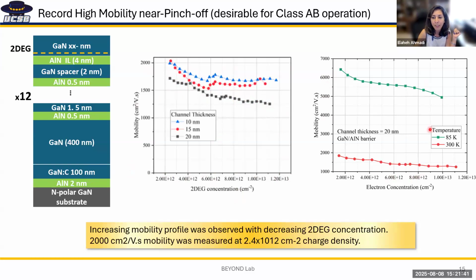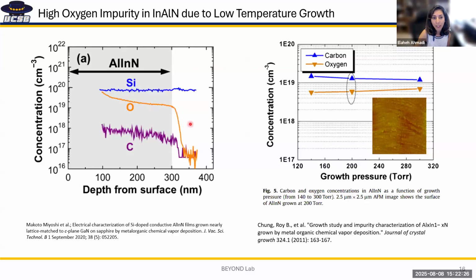And when we perform these measurements at low temperature, because then we are eliminating optical phonon scattering and all that, it's easier to see if things like ionized impurity scattering or interface roughness affect the mobility. And we saw even at low temperature, as we go to lower charge densities, the mobility increased. So we were quite excited about this, and we showed a record mobility of around 2000 near pinch off. But then the question was whether this is due to the barrier, that we have a digital barrier. So we worked on indium aluminum nitride.